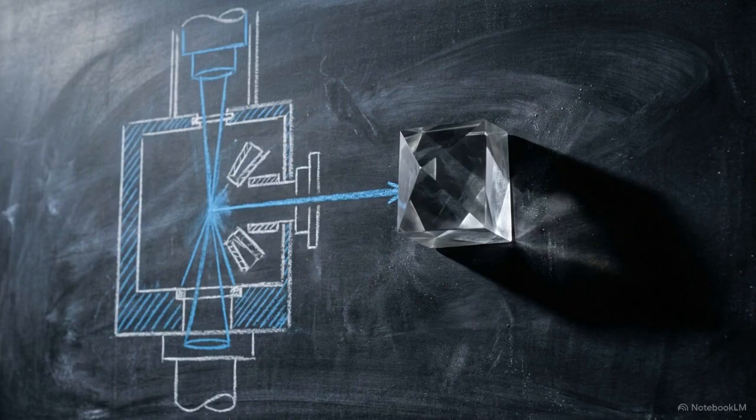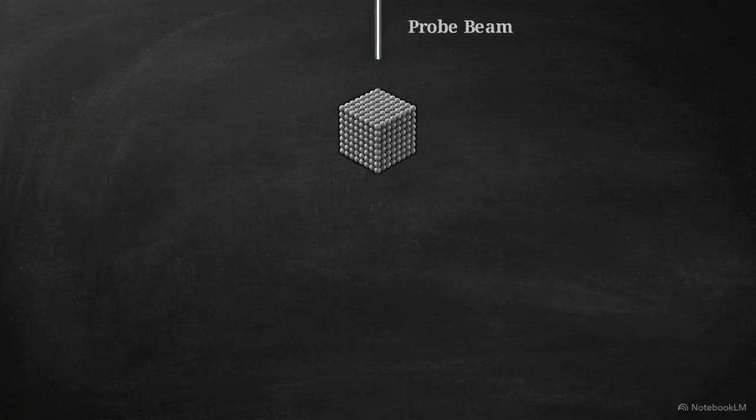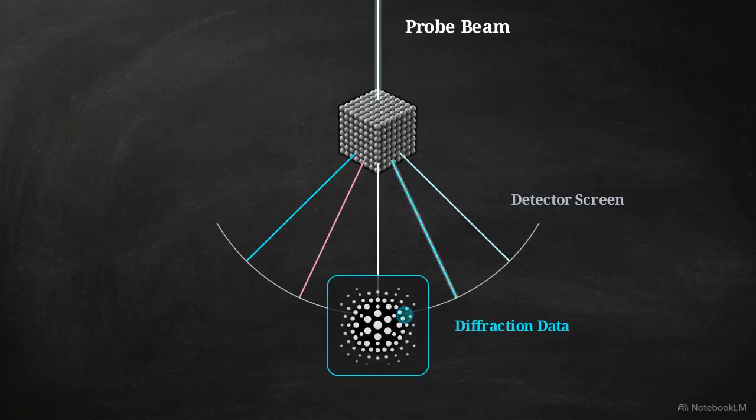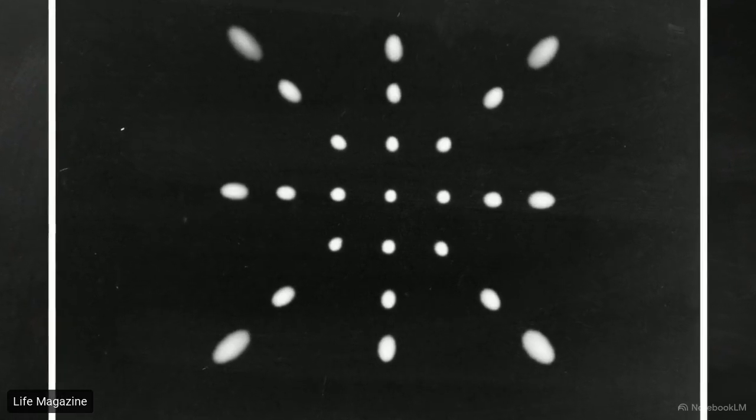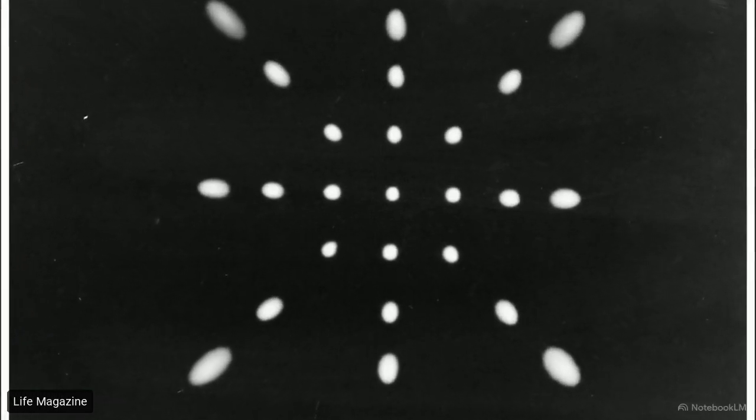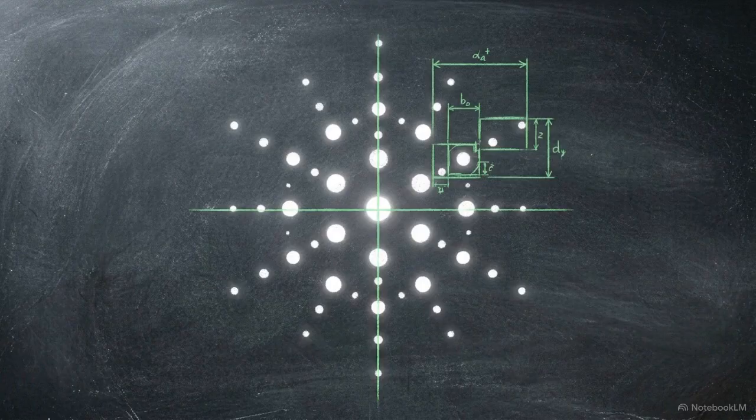Modern methodologies like 4D scanning transmission electron microscopy and dark field X-ray microscopy attempt to isolate this charge by mapping the crystal's response to electron or photon scattering. This image shows a luminous symmetric grid of diffraction spots generated by empirical reciprocal space data. By analyzing specific diffraction vectors, microscopists test contrast conditions to isolate and classify individual defect properties.